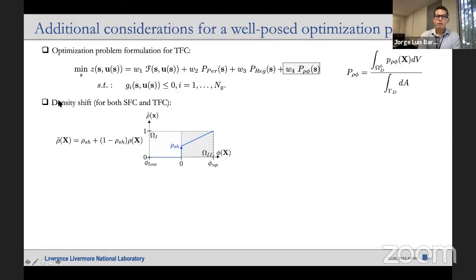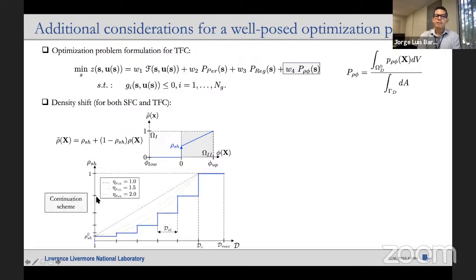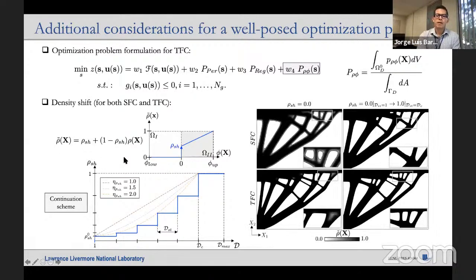And we do this by introducing this density shift. The idea here is that there's this parameter, rho sh, that through a continuation scheme goes from a very small value to one, such that at the end of the optimization problem, you have this completely independence of the density field rho of x, because this density, the one that you use to interpolate your material properties, is going to be equal to one. And the effect of this can be seen here in this example.